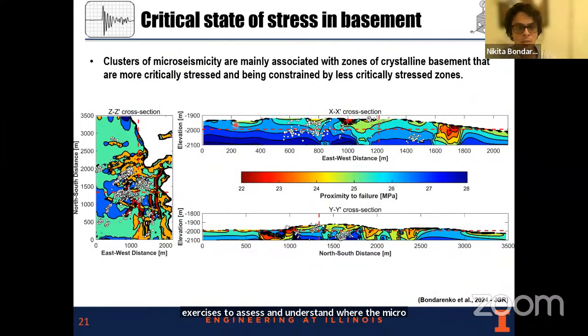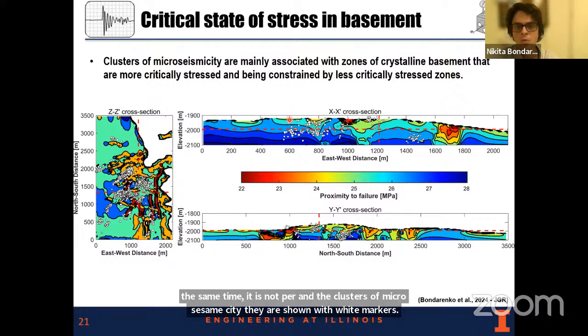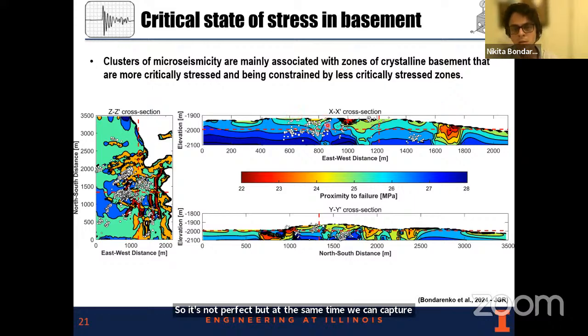On the previous slide, it was vertical in map view. These are the two vertical cross sections. We predict some zones which are more critically stressed, shown with red and warm colors. At the same time, the clusters of microseismicity are shown with white markers. It's not perfect, but we can capture at least some localization - they have a tendency to be localized in more critically stressed zones.